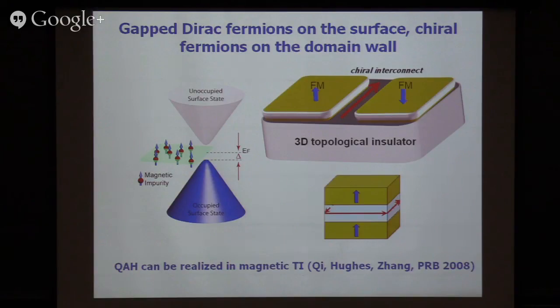But that immediately leads to something that goes beyond the original field of time reversal invariant topological insulators. So imagine I have this Dirac cone, and at the Dirac point, the gapless nature of this Dirac cone is protected by the time reversal symmetry. But now imagine that you coat the surface of a 3-dimensional topological insulator with a thin magnetic layer. It could be doping the material with some magnetic atoms, putting on a ferromagnetic insulating film, and so on. But then nature usually, if by symmetry it's allowed, it will happen. So by having a magnetic layer on the surface, it will break the time reversal symmetry.